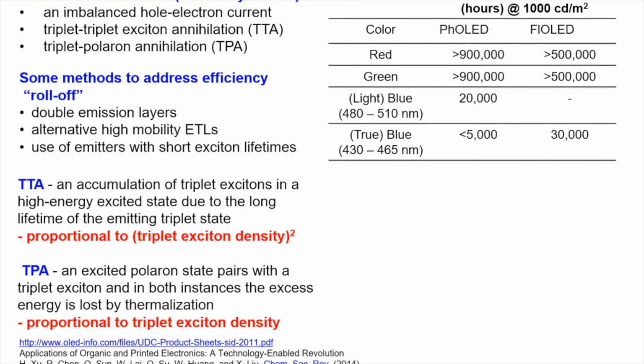The causes of the instabilities of blue organic light emitting phosphors that go into the blue component of the OLED are mainly caused by an imbalanced hole-electron current, triplet-triplet exciton annihilation, and triplet-polaron annihilation. And many researchers have looked at ways to solve these issues. Some methods that have been developed are double emission layers, grading the emissive dopant, alternative high mobility electron transport layers, as well as use of emitters with short exciton lifetimes.